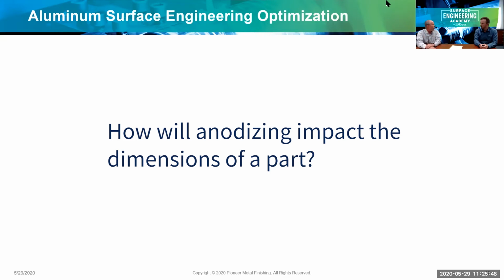So if I was going to put a thousandth of an inch of anodizing on, I would approximately change the dimension 3/10,000ths of an inch per side. Now, hard anodizing, type 3 anodizing, is closer to about 50% growth, 50% penetration. So do need to keep that in mind when you're looking at parts that have tighter tolerances. Planning for extra dimensional growth, but not like a plating where if you asked for 2 mil, you get a full 2 mil growth per surface. Correct. So again, 70% penetration, 30% growth for type 2, and then 50-50 for the type 3 hard coat.